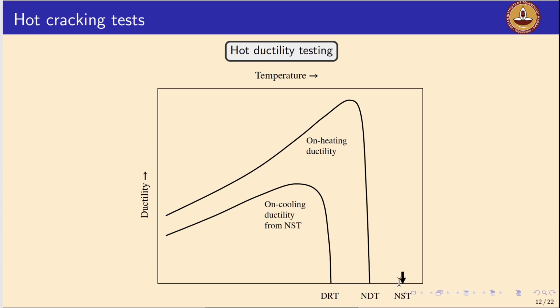And subsequently, when we start cooling the weld and do the testing as a function of cooling temperatures, we can identify the ductility recovery temperature, the DRT. Again, they are indicative of the solidification range over which the weld is cooling and then subsequently solidifying completely into a solid structure. So if the difference between the NST and DRT is larger, then we can say that the material is solidifying over a larger range. So the solidification cracking susceptibility temperature range would be larger. Therefore, the material can be susceptible to hot cracking during cooling. So the difference between these temperatures gives us a good indication about the hot cracking susceptibility of the material.